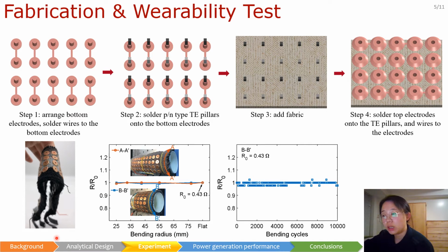Wearability-wise, the photo here shows how flexible the device is. We have measured the electrical resistance of the device before and after bending. The normalized resistance against bending radius and bending cycles are given in the bottom right. We can see that the resistance of the device stays the same at different bending radii in the range of millimeters along two directions, AA and BB indicated in the insets, and also after 10,000 times of bending, which indicates the device should be able to sustain more than 10,000 times of wear.